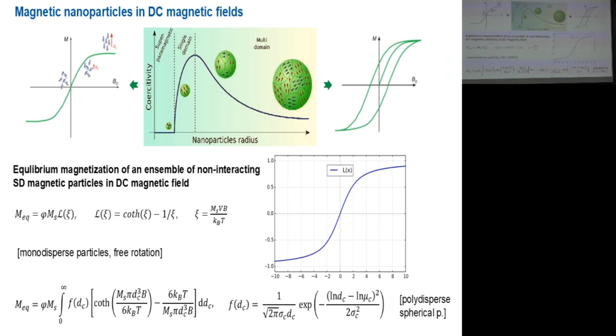Nevertheless, in typical samples you have some size distribution, as we saw in TEM. And you have maybe made some assumption regarding the size distribution, like with the log-normal distribution. So you may need to do integration of the Langevin function over the given size distribution. So you may describe the magnetization of the sample by such a simple equation, and the crucial parameters come from transmission electron microscopy.